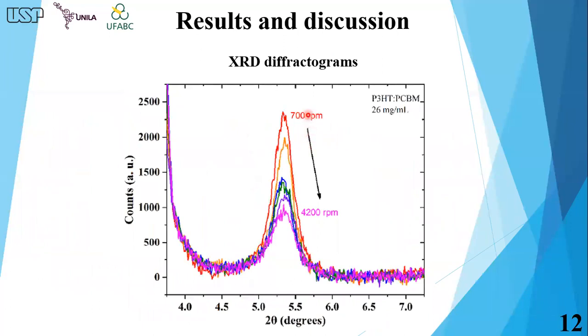Diffractograms show a peak at 5.3 degrees, typical of P3HT (100) with lamellae perpendicular to the substrate. The intensity of this peak decreased with increasing spin frequency. This is a sign of lower crystallinity at higher deposition frequencies. On the other hand, blade coating is probably forming films with more crystallinity. High crystallinity films are desirable to improve charge transport after exciton dissociation.